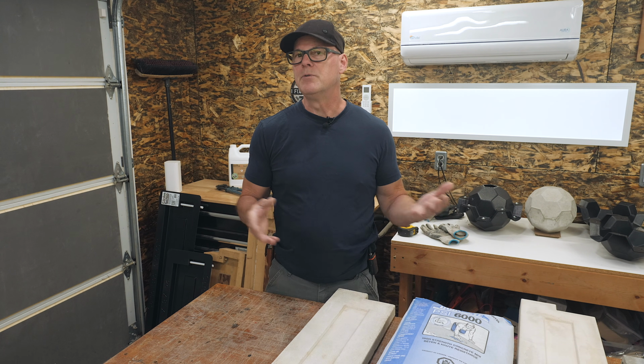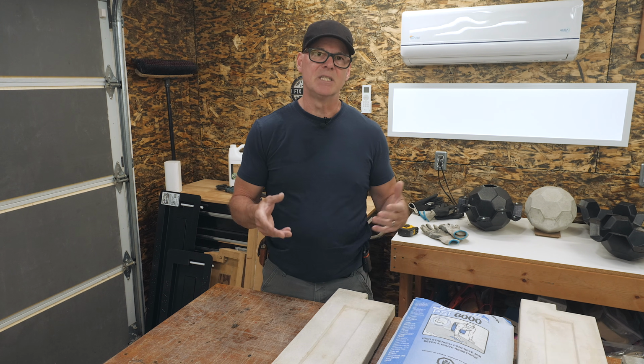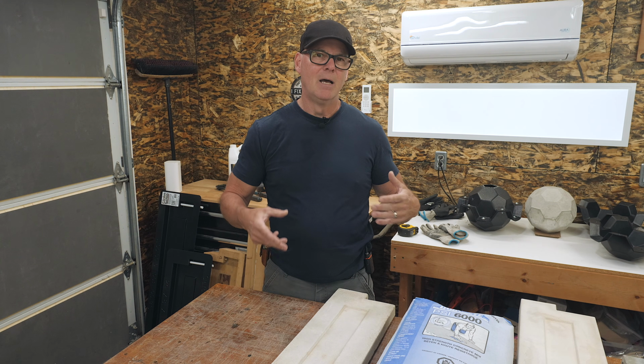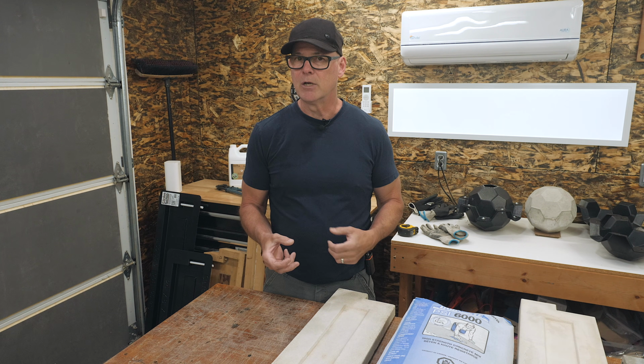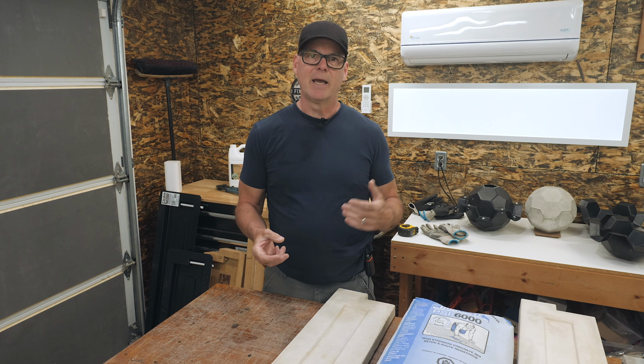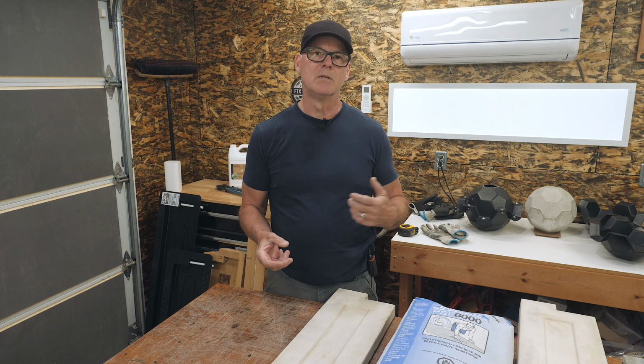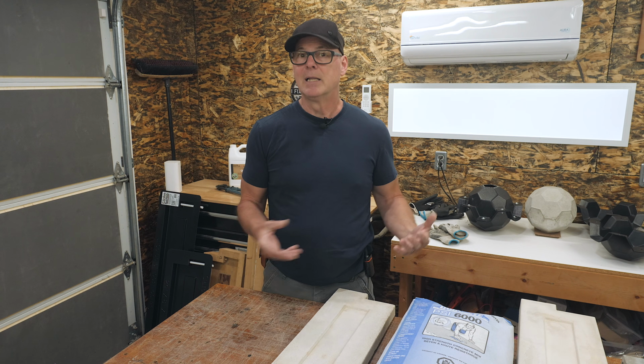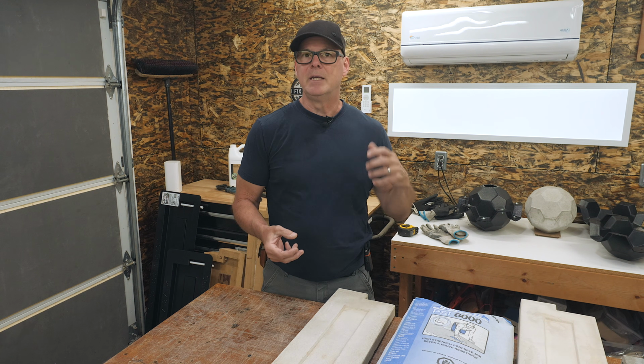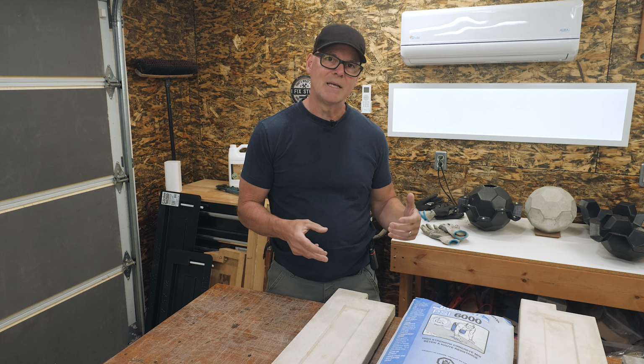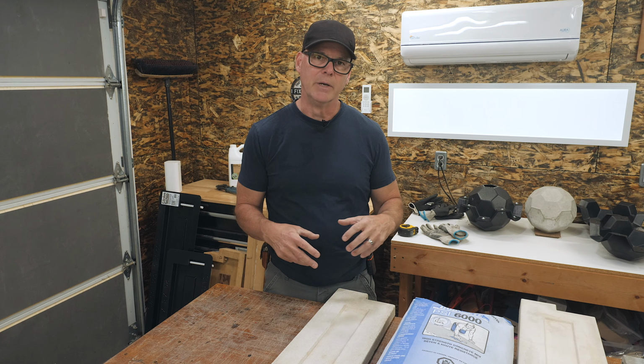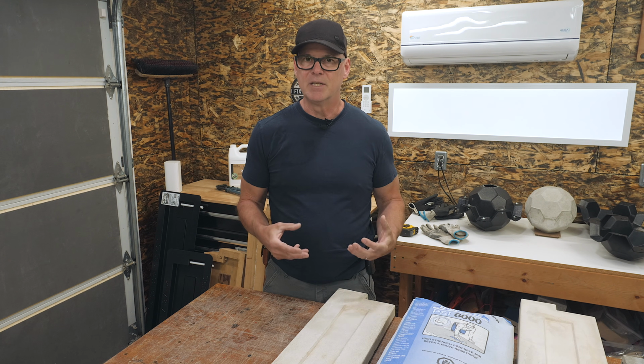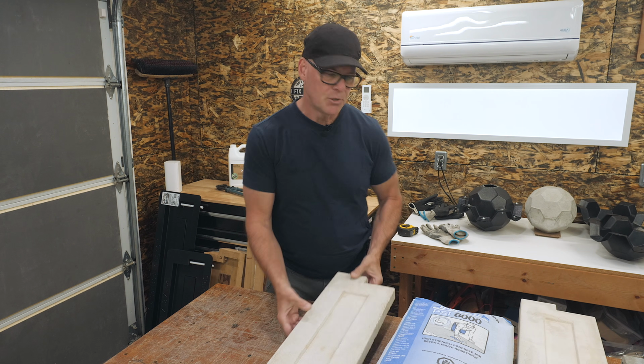When I moved to the plastic molds, I found that the CSA mortar mix generated a lot of heat as it cures very quickly. This excess heat can have detrimental effects when it's not absorbed by its surroundings, like it does with the wood molds. The heat goes into the wood, where in the plastic molds the heat stays in the concrete, and that can cause it to create some surface cracks. Let me show you.